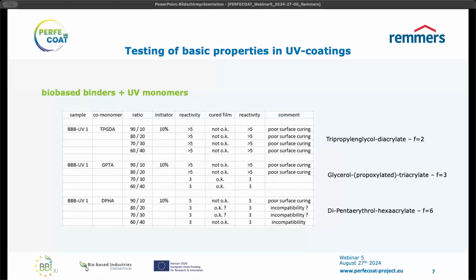When we changed to the hexafunctional co-monomer, the curing performance did not really improve much more. But the film wasn't looking really homogeneous anymore after a certain addition. So there seems to be a point when it comes to some incompatibility effects.